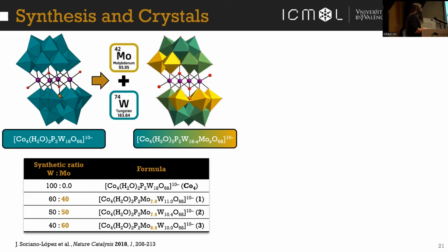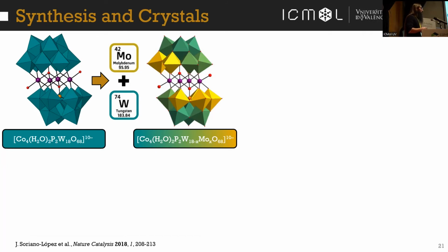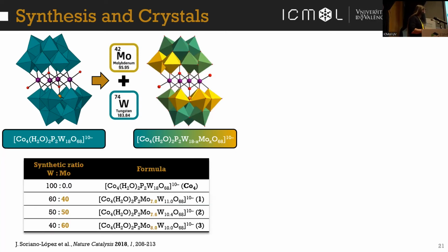So for doing this, the idea was to take the synthesis of the cobalt-4 and replace some of the tungsten by molybdenum with different synthetic ratios. And we were lucky to obtain reproducible results with 3 different ratios. So as we can see, when we increase the amount of molybdenum in the synthesis, we could also increase the amount of molybdenum in the crystal structure.